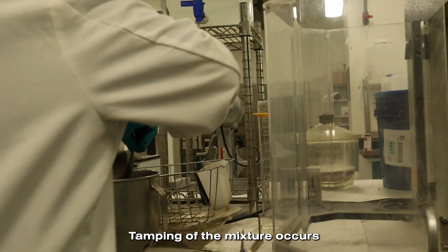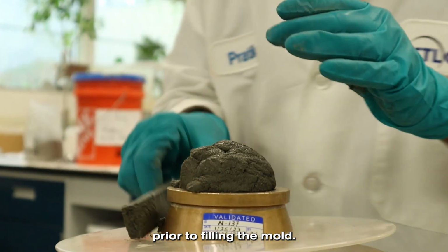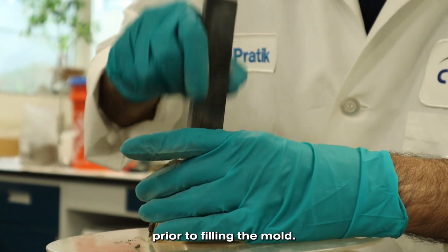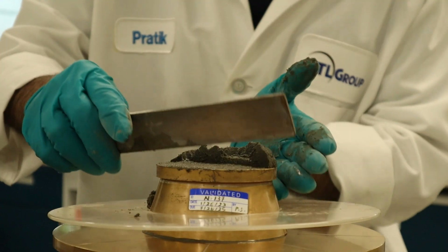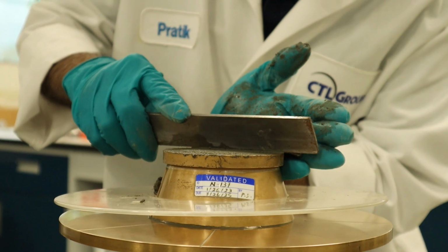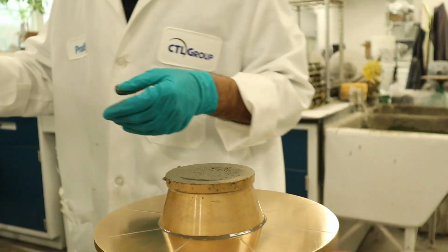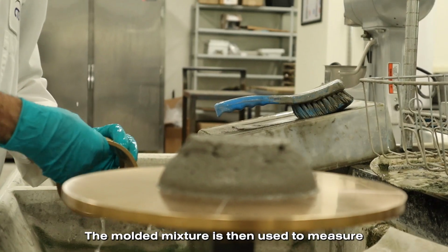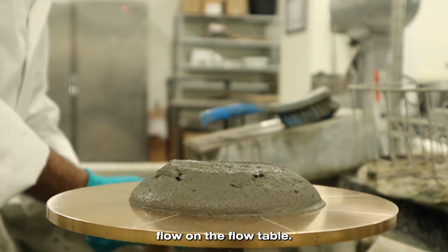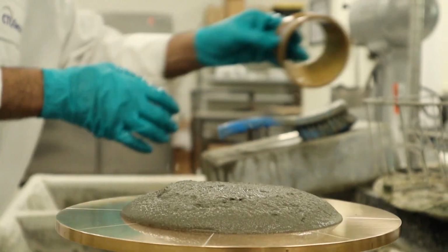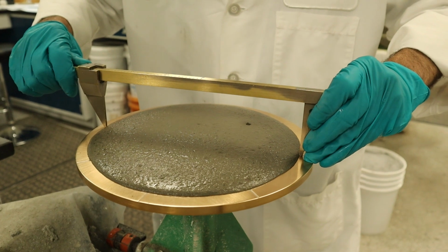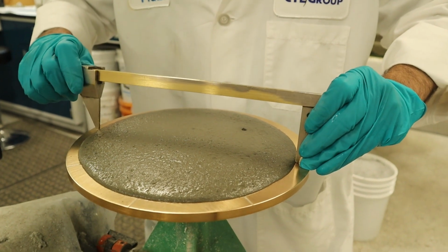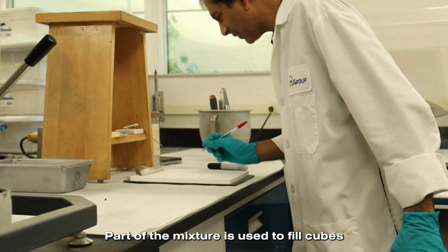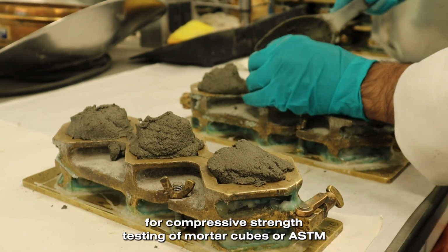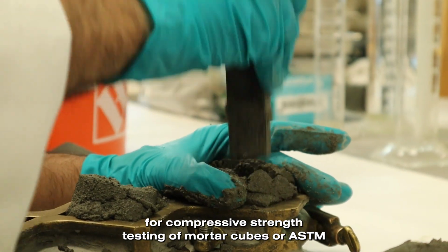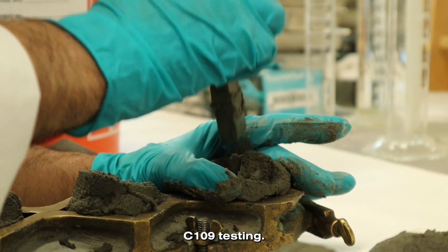Tamping of the mixture occurs prior to filling the mold. The molded mixture is then used to measure flow on the flow table. Part of the mixture is used to fill cubes for compressive strength testing of mortar cubes, or ASTM C109 testing.